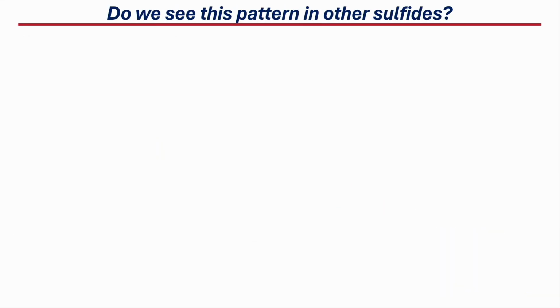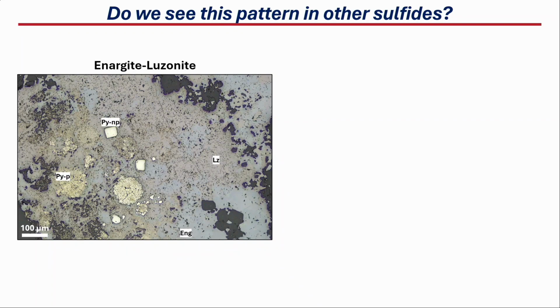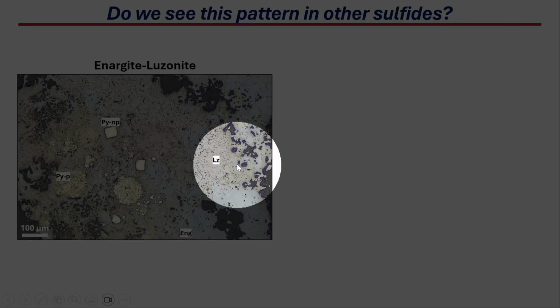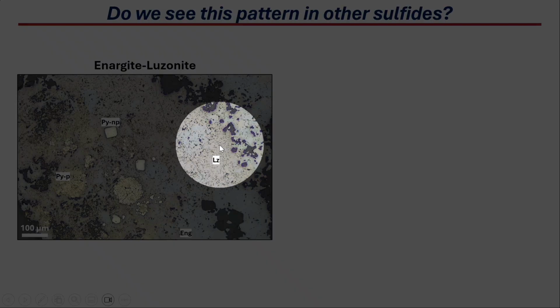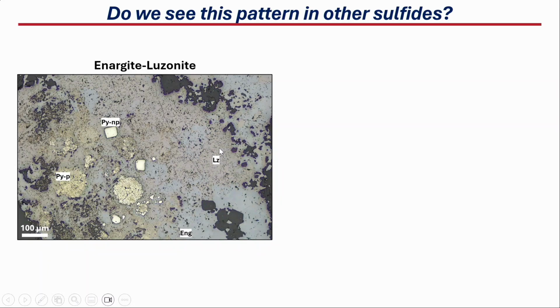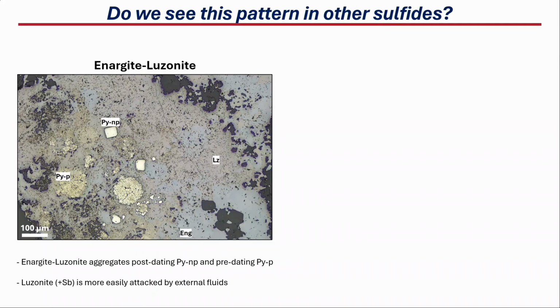Now, just to support this idea, have we seen this in other minerals? And yes, we have seen that in enargite mainly, which is associated with pyrite. In this image, what we can see is a massive aggregate of enargite and luzonite. So they are polymorphs. What we can see over here in this purplish color is enargite. The pinkish is luzonite. And if you see the texture, usually luzonite is more porous than the enargite. Well, that can happen. We actually don't know that completely, but maybe it's because luzonite has more antimony and it can be easily remobilized.